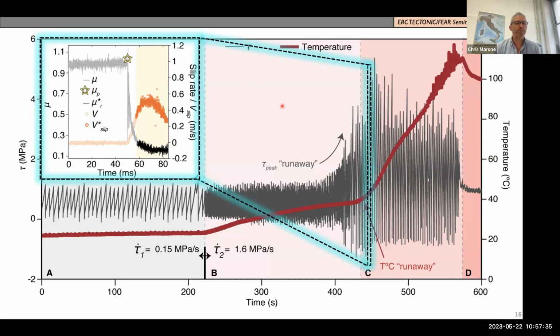But this means, Ethan, that your slip velocity is not directly controlled by the rate of displacement, because you measure it for the energy or not? So we're calculating the energy from the slip velocity; it is part of how we're calculating the power density or the energy dissipated by friction. Okay, that's fine, because I need to understand if you have some smearing in your calculation. Okay, thanks. No problem. Thank you. Of course.